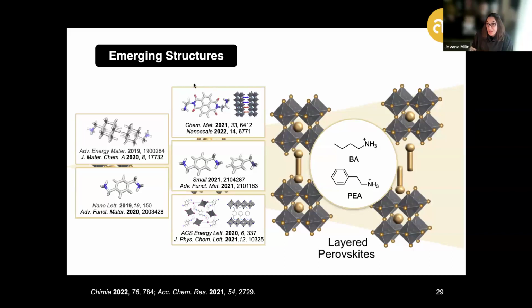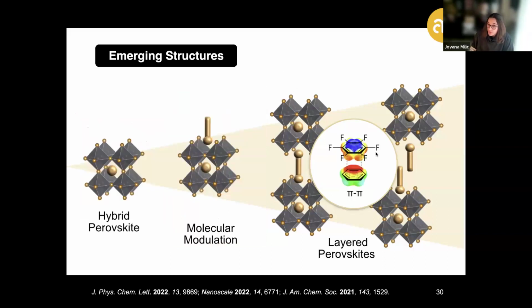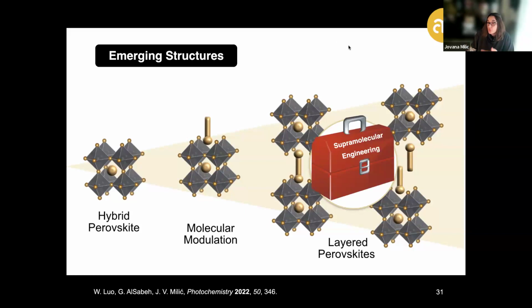These phases are not as prominent compared to Ruddlesden-Popper systems, and we further expand their scope by introducing additional aromatic units or functionalities, such as different heteroatoms, including perfluorinated aromatic modification that changes the polarity of the aromatic group, enabling more robust pi-based interactions within the organic component, which increases stability and makes for more robust structures, enabling better understanding of the gauges used to tailor structural properties and emerging functionalities.